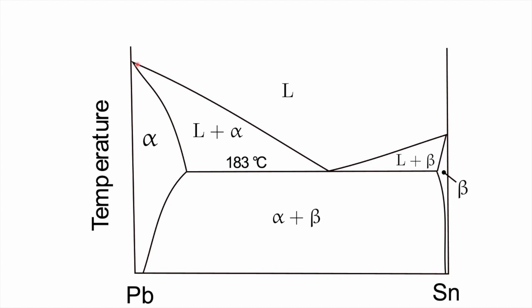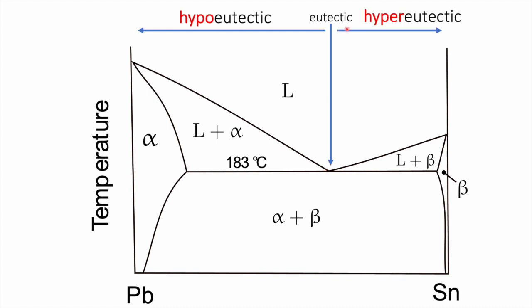Now, over here, you can see that as the concentration of tin in lead increases, we get a reduction in the melting temperature. Similarly, when the concentration of lead in tin increases, we get a reduction in melting temperature. And there is a point here where, if you cool the liquid, it will decompose simultaneously into a mixture of alpha and beta over a very, very narrow temperature range. So this is known as a eutectic composition, where liquid decomposes into a mixture of alpha and beta. This is the eutectic composition, and this is the eutectic temperature of 183 degrees centigrade.